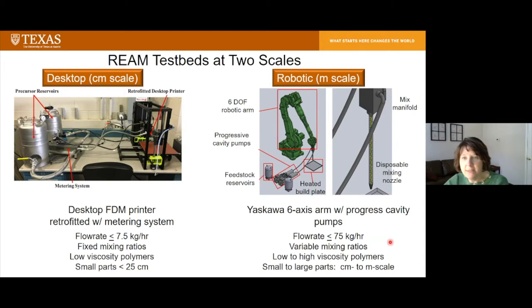The flow rate in our robotic system is really high. We can get up to about 75 kilograms per hour there. And so that's on the order of the very fastest systems out on the market. So for example, BAAM, the Big Area Additive Manufacturing system that's been commercialized out of Oak Ridge National Labs, has a similar level of flow rate. We can do variable mixing ratios, high viscosity polymers up to about 100 Pascal seconds. And we can do larger parts with this, smaller parts as well, centimeter scale, but also meter scale parts because of the robotic arm.